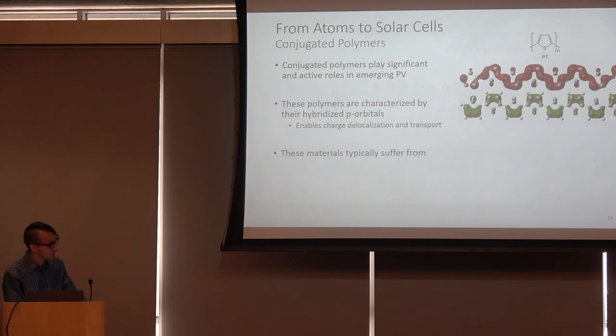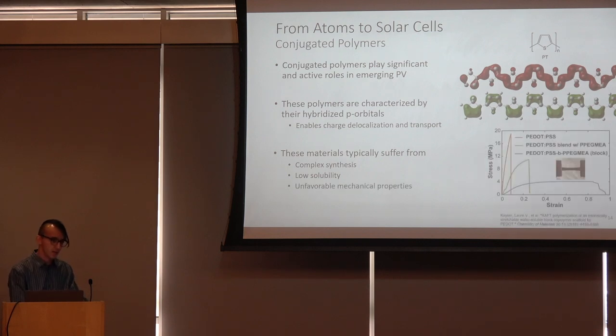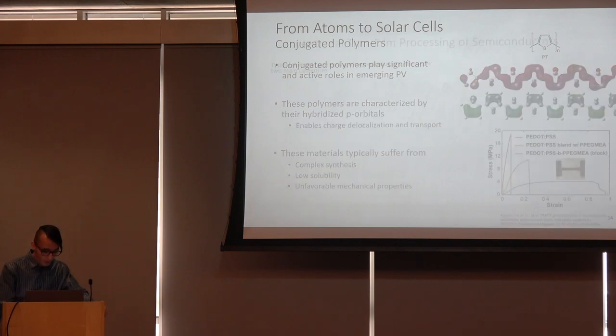And these materials typically suffer from complex synthesis, low solubility, and then unfavorable mechanical properties. Typically, when you increase the solubility or improve their mechanical properties, this comes at the expense of the electronic and optical properties. And one of the central focuses of our group has been in getting sort of the best of both worlds without having to compromise too much on either.